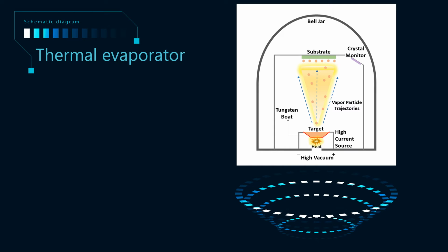This schematic diagram represents our thermal evaporator setup. The powdered manganese oxide and vanadium oxide were compressed into circular pellets. These target pellets and the aluminum substrate were placed inside the thermal evaporation chamber under a vacuum of 10 to the minus 4 torr.